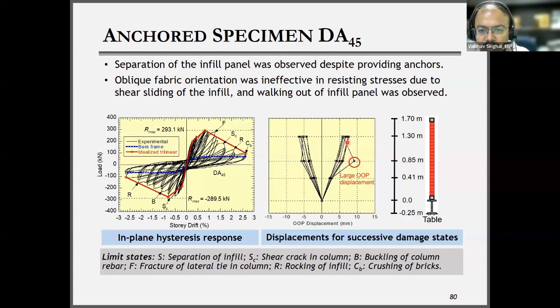But what we have seen is that because the fabric is taking the maximum forces, we have seen early rupture of the fabric, because of which at some places we have seen some large out of plane displacement, because of the early failure of the fabric during the in-plane cycle.